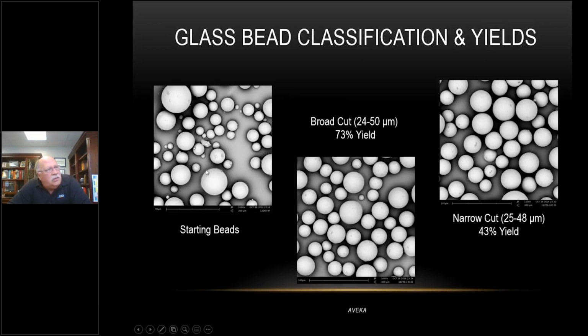Here's the SEM picture, so you can see that the broad and the narrow cut look about the same, maybe a few smaller particles in there, but look at the yield on the broad cut versus the narrow cut. A 3 micron difference is almost double the yield. I put this example in here for everybody to understand that being a little flexible on what process parameters and what final product parameters you want can have an incredible effect on the final yields. Many times we have people come in who have identified that they want this narrow cut and won't look at what happens if we just broaden it out a little bit, but the effects can be spectacular.